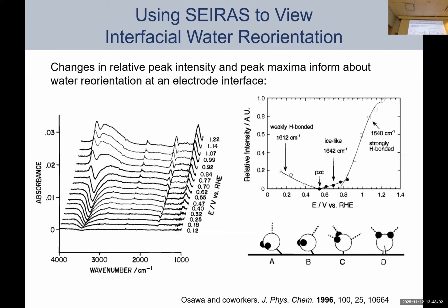So you can actually see this if you take, I think these are recorded on a platinum surface or possibly gold. Sorry, my bad, I forget which one, but I think possibly gold, in sulfuric acid. And so you can see these dramatically different water features as a function of applied potential. So here it's more negative applied potential going towards the top and more positive applied potential going back. With respect to a reference potential around 0 volts versus RHE, you see these dramatic changes in both the OH stretch and the OH bend, which is right here. Okay, so how do we explain this?